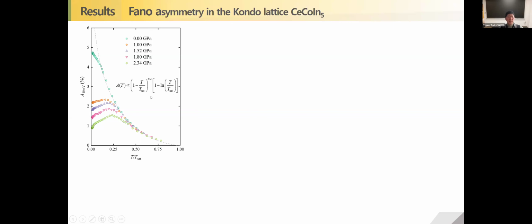So this is the scaling behavior of the asymmetry as a function of reduced temperature, where the temperature is divided by the so-called saturation temperature. The asymmetry is evaluated at 10 millivolts. This is ambient pressure, and then this is 1 GPa, 1.5, and those pressures. As you can see, at higher pressures they all collapse together, and with increasing pressure the deviation temperature is enhanced.